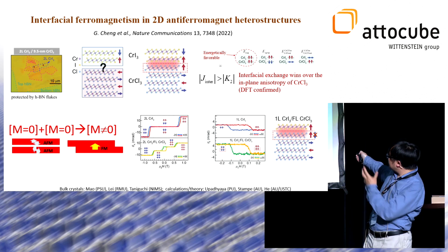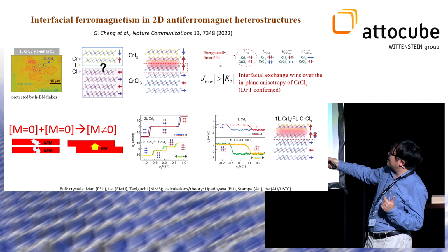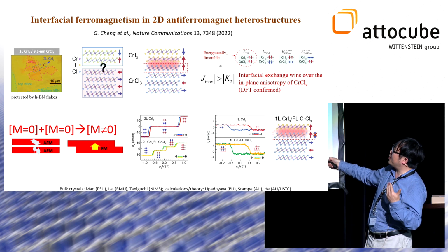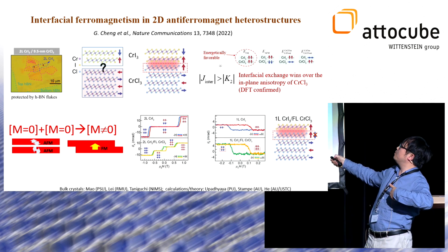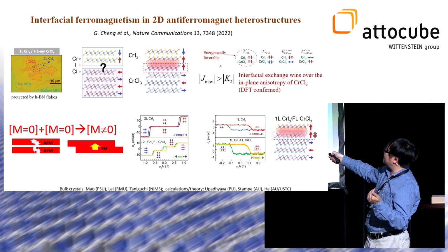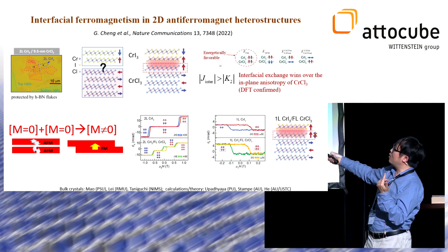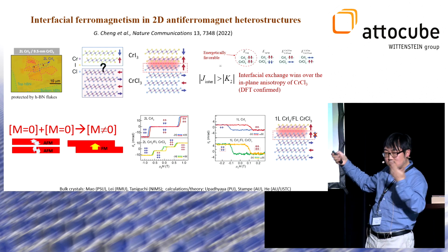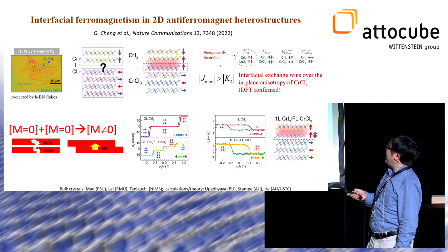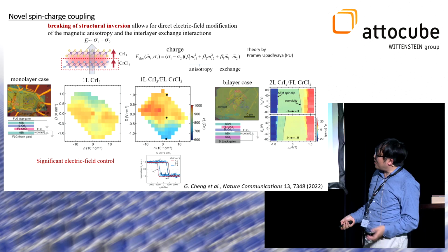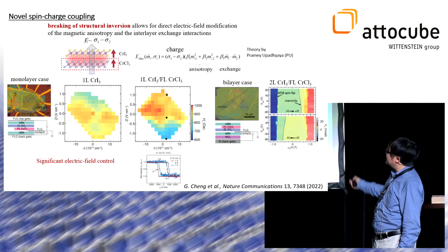What happens, supported by DFT calculation, is that this layer of chromium chloride actually makes its neighboring layer of chromium iodide more listen to itself. It actually rotates its anisotropy to be ferromagnetically coupled to this chromium iodide. So this interface emerges with these ferromagnetic responses. And yet, no surprise, again, we always build devices, we never do these measurements alone.